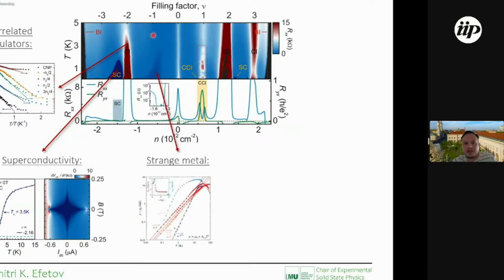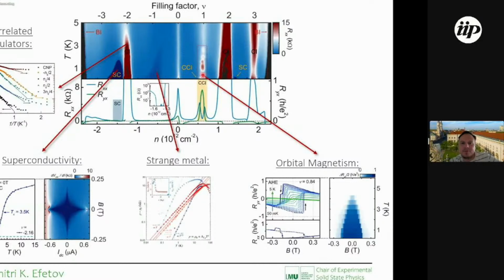Then if we zoom in a little bit into the center of the phase diagram at arbitrary fillings, so away from any integer filling factor, we can observe strange metal behavior. Moreover, at a filling factor 1 here, for example, we can observe a magnetic signal. So basically, we can observe this when we measure the Hall voltage as a function of magnetic field, whether we sweep the field up or down. We can observe these hysteretic jumps. And what's special about this is that this magnetism is now understood to be not spin magnetism, so not ferromagnetism, but rather orbital magnetism, which is given rise by symmetry breaking and valley polarization of the bands.